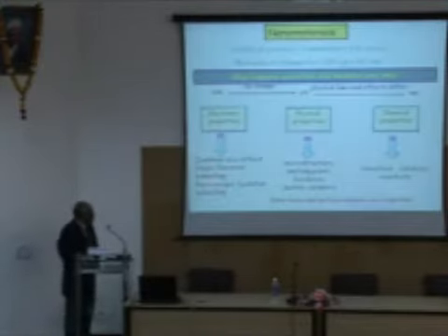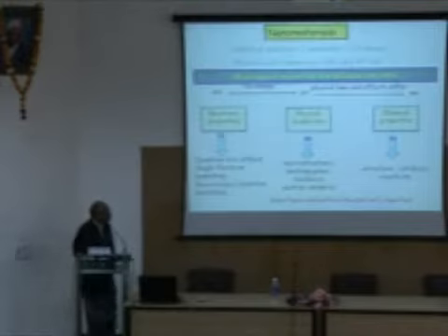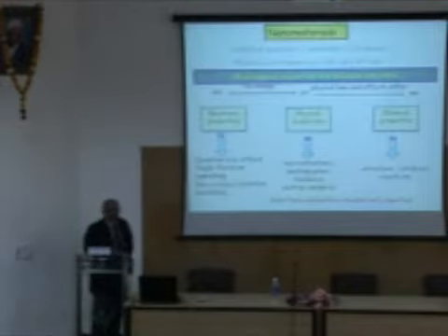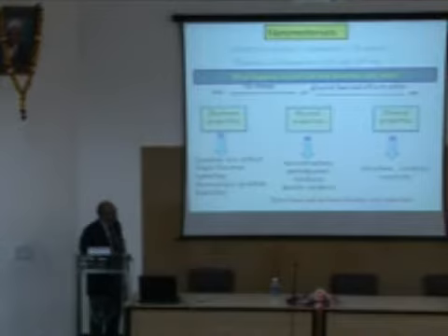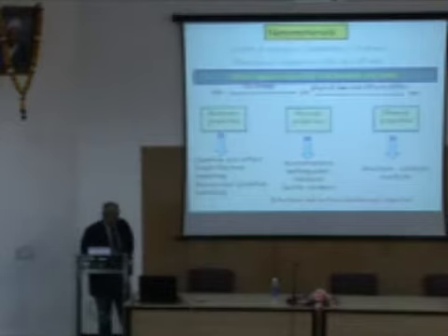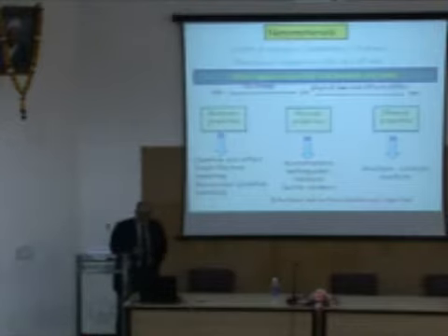If you are a material scientist, you know you have changes in the microstructure: the melting point reduces, the ductility changes, the hardness changes. From the activity point of view, your structure can change and your catalytic properties certainly get enhanced. The surfaces and interfaces become important because the size of the particles is so small that there are hardly any particles in the bulk.